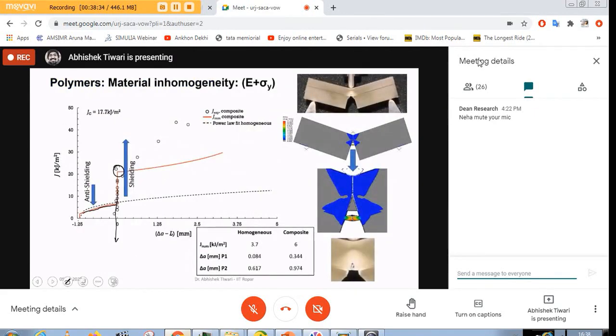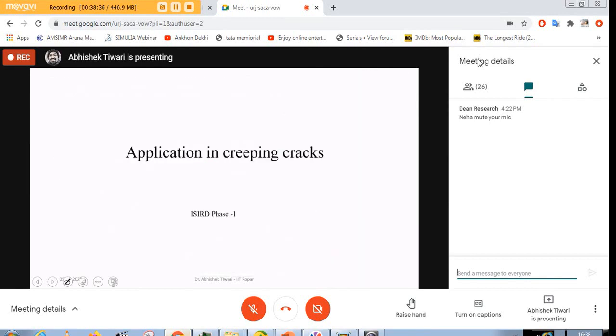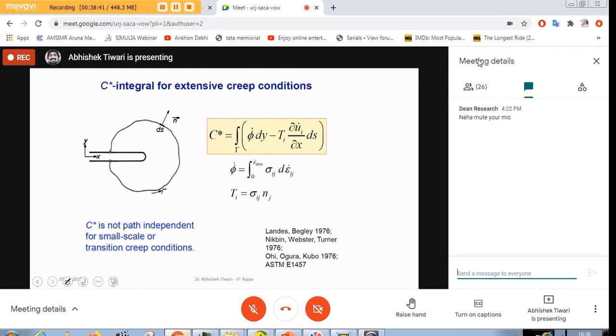After joining IIT Ropar, I have applied this concept to creep deformation. In creep deformation, we have a close cousin of the J integral. If you remember, the J integral was simply a line integral having strain energy density, traction, displacement gradient, and the contour path. And this is a close cousin of that. So whatever parameters are time dependent, we use a rate. Not we, but fracture mechanics people use the rate of that. So phi dot is simply d phi by dt, and u dot is simply del u by del t.